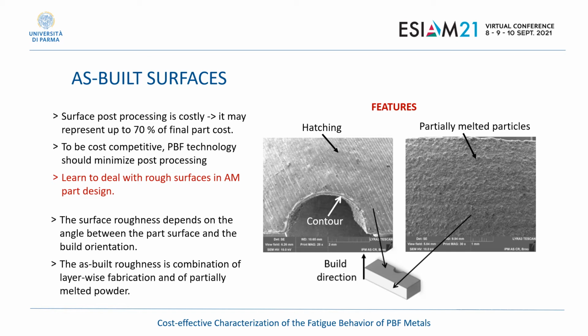Here we see the characteristics of the as-built surfaces. As shown in the picture, we have, for example, hatching configurations, we have contour patterns, and also we can see on the right side how the surface is rough because of partially melted particles attached to the surface. We can also recognize how the orientation of the surface with respect to the build direction generates features that are completely different, and therefore we can expect that the fatigue behavior is influenced by it.